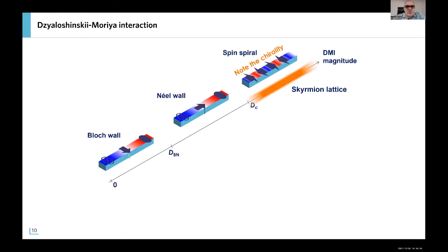So just a few words about why this Dzyaloshinskii-Moriya interaction is important in today's nanomagnetism. If you consider, for example, a stripe with perpendicular magnetic anisotropy, two domains, up or down, are separated by Bloch domain walls if you have zero Dzyaloshinskii-Moriya interaction. But then if the Dzyaloshinskii-Moriya interaction increases, the Néel domain wall, so this configuration inside the domain wall, will become favorable. And if you keep increasing the Dzyaloshinskii-Moriya interaction, the most favorable configuration becomes a spin spiral state with a given chirality that is directly linked to the sign of the DMI.